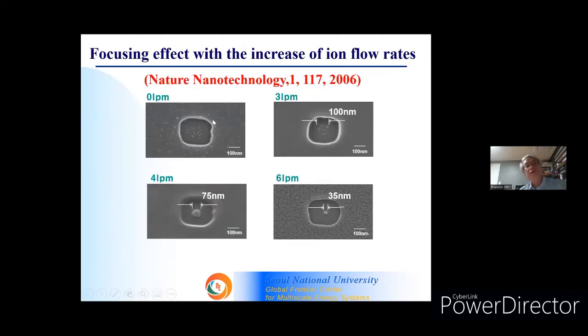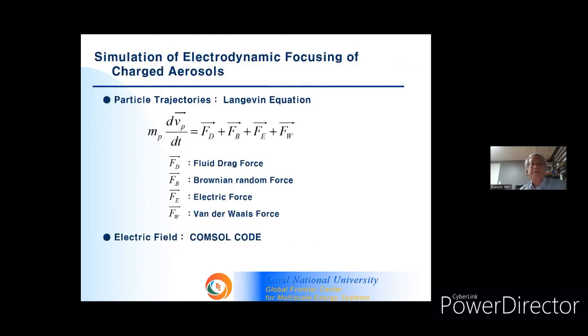If you increase ion flow rate, you can control the focusing extent. At 0 LPM particles deposit everywhere, at 3 LPM particles are confined within 100 nanometers. You can see several particles deposit on the surface of PR. At 4 LPM, 75 nanometers; at 6 LPM, 35 nanometers. Again, 35 nanometer is not a single particle, but multiple deposition of 10 nanometer silver particles.